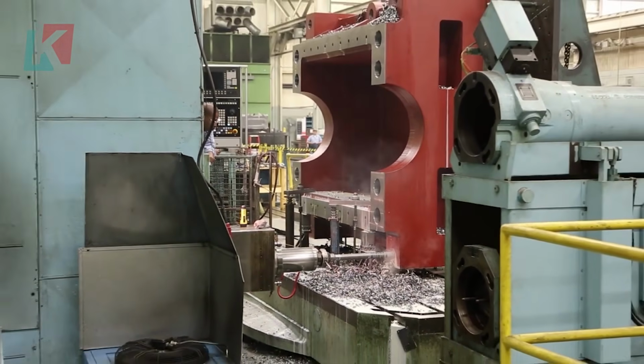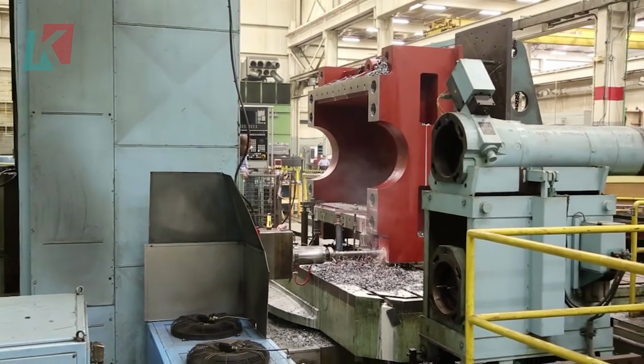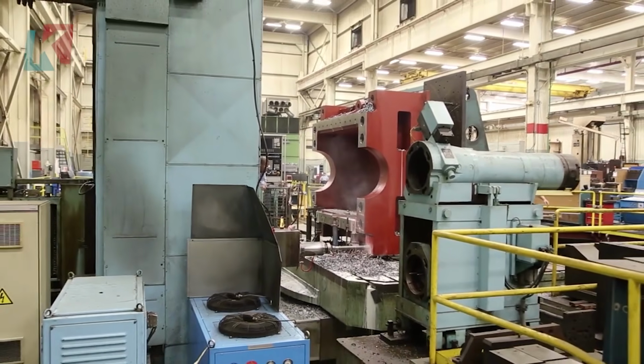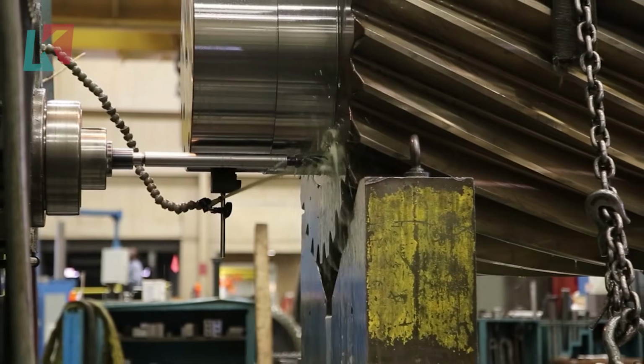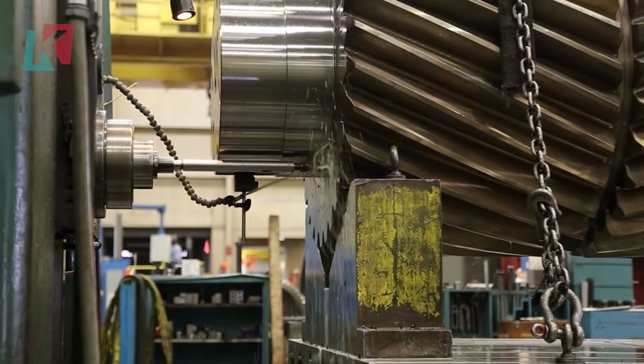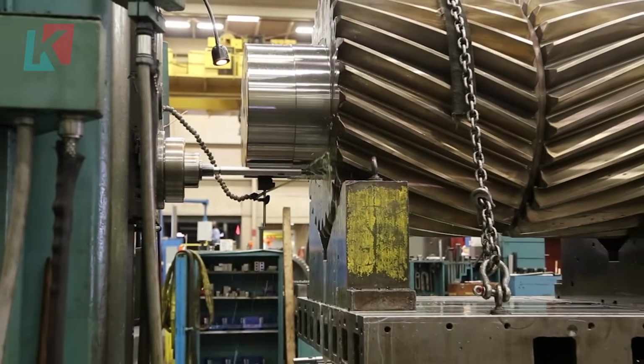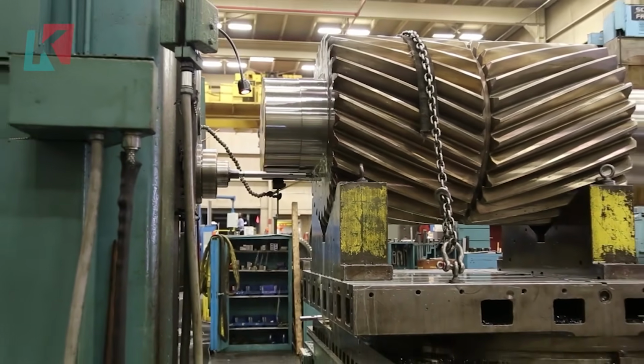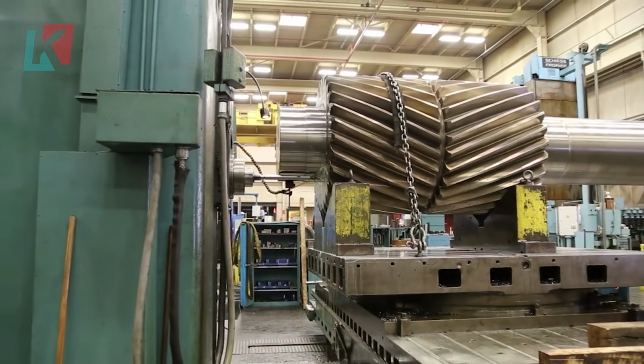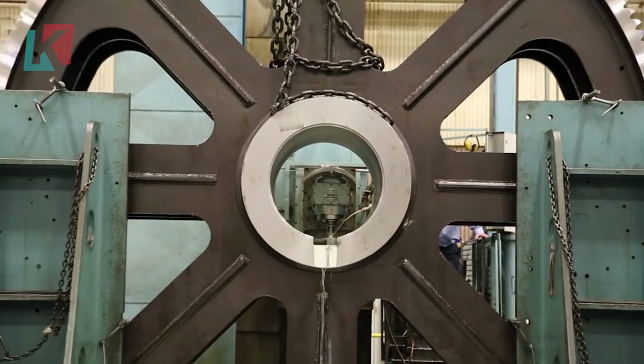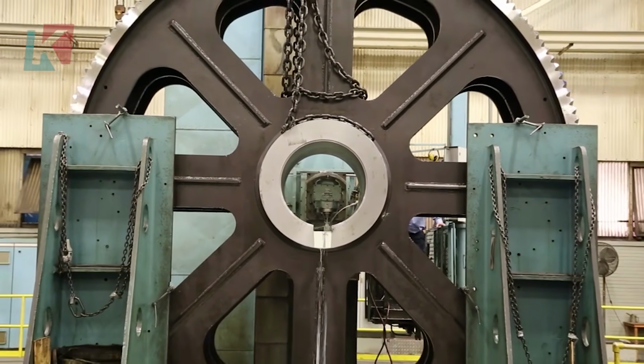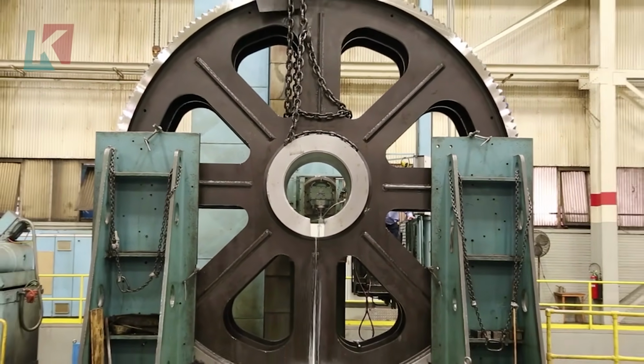The quenching process is critical. Imagine trying to cool a 20,000-pound gear uniformly. They use specially designed quench tanks with circulation systems that ensure even cooling. Too fast, and you get distortion or cracking. Too slow, and you don't achieve the required hardness. The tempering process that follows relieves stress and optimizes the balance between hardness and toughness.